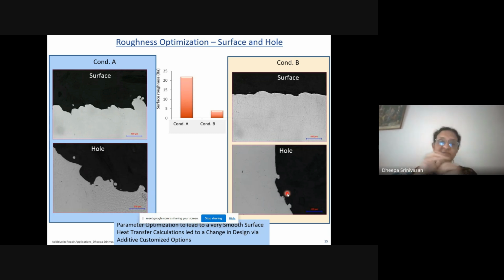However, if you're having an internal surface, first of all, inspection is very difficult. The previous speakers in the course might have highlighted those as one of the big challenges. Yes, it is a challenge because we can't cut up every single part. Even if we cut it up, how do we know the cut up portion is the location where we are having these roughnesses? So one of the things to do is to develop intelligent gauges which can physically measure the surface roughness of the built part, especially in geometry such as cooling holes, and then pair it up with numerical calculations and flow physics calculations to make sure there are no hot spots or constriction of the cooling hole, leading to less air passing through it, and so on and so forth. So heat transfer, that's what we did.